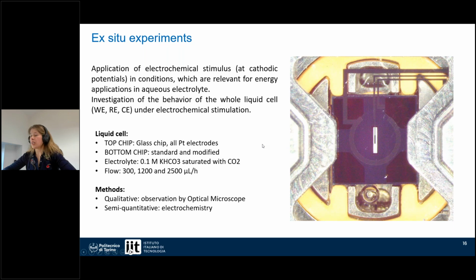So I will show you the results when we apply some electrochemical stimuli at cathodic potentials. And we will investigate the behavior of the whole liquid cell under the electrochemical stimulation. I just want to add that we have studied various flow rates to understand also the influence of the flow rate for this. And these experiments were done in the electrolyte saturated with CO2. We are interested in the applications for CO2 reduction reaction. So as I show, with this glass chip, we can have access to all electrodes. And this is the area which we could have observed if the top chip was made of silicon, so if it was a standard chip.